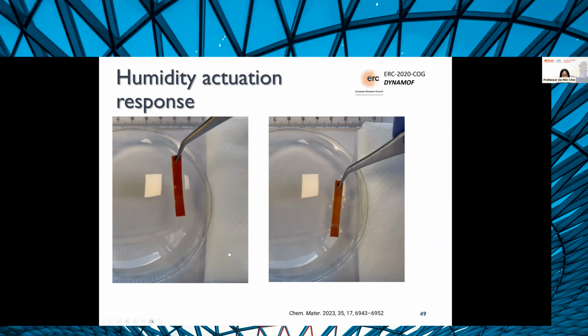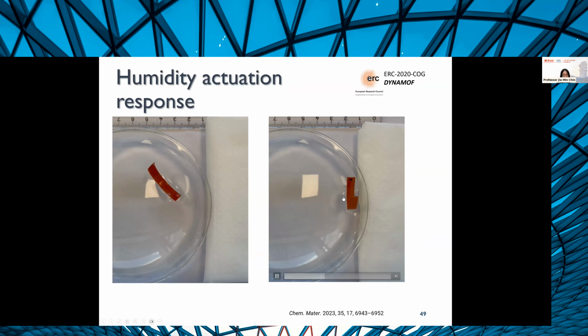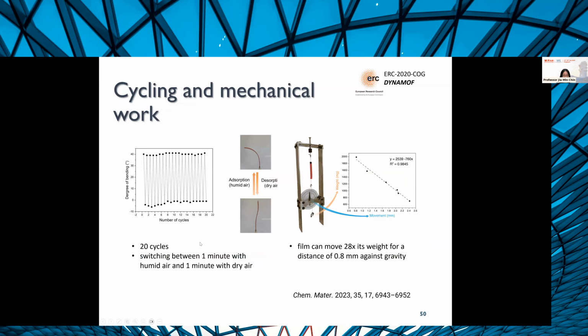Here are a couple videos. So here you have the unaligned and here you have the aligned. And not only do you see that there's a difference in the extent of the curling behavior, but also a difference in how fast it actually starts to curl. And we saw that we can actually cycle this, like it can absorb and straighten over 20 cycles. And then I think the postdoc got a little bit fed up with continuing this, but probably could go further.